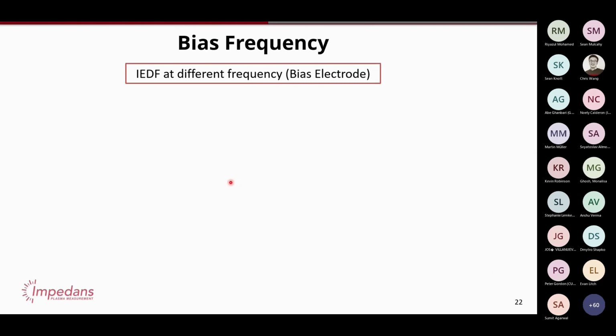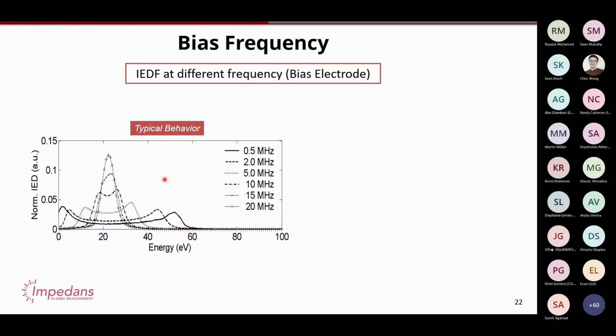Bias frequencies. We're getting close to the end. So what happens if you don't use 13.56 megahertz? What happens if you use 2 megahertz, 400 kilohertz? What happens if you use 60 megahertz? Why do you use different frequencies? This graph, I think, tells the story pretty well. The higher the frequency, the less chance the ions have to react to the RF voltage going up and down in its cycles. So at really high frequencies, it almost looks like the electrode is a DC sheath. You get this sort of single peak.